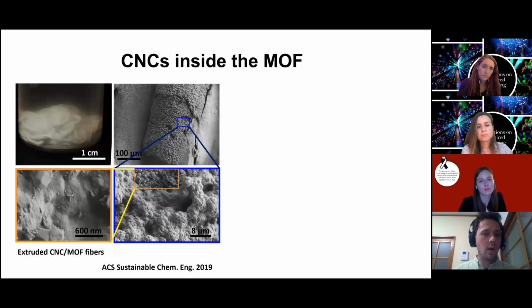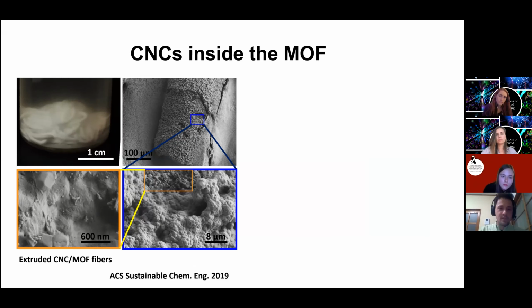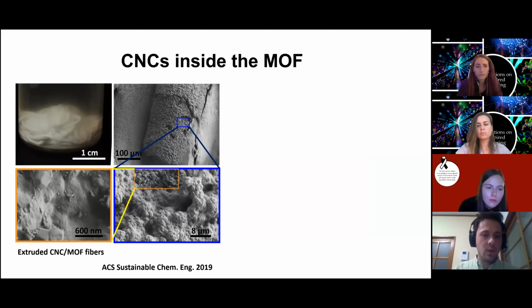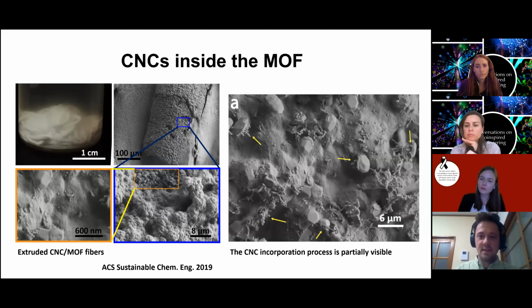That really strong white is coming from that metal organic framework. It scatters a lot of light, so it looks very, very bright white like milk. And if we zoom in on those fibers, we can see that we have these crystalline particles there. What's even cooler is we can actually see the individual cellulose nanocrystals, and sometimes when they assemble into fibrils, interacting with the MOF. And the MOF, if we freeze this in time, we can actually see that these MOF crystals are growing truly around those cellulose nanocrystals, and that it's almost like fingers that the MOF is growing around.